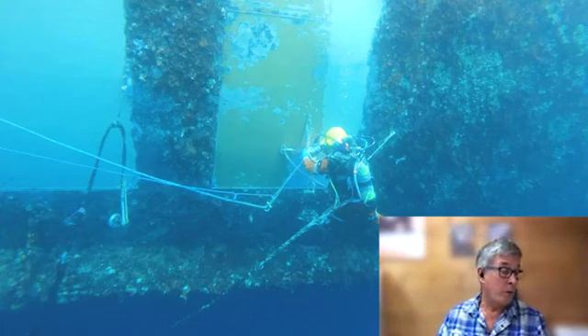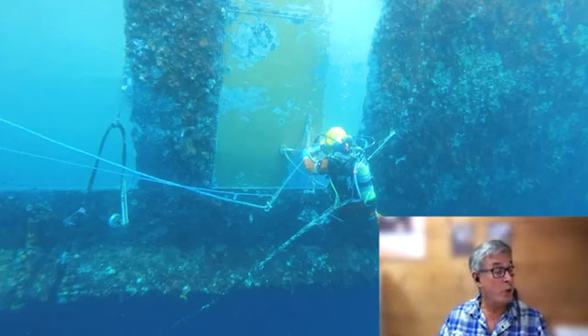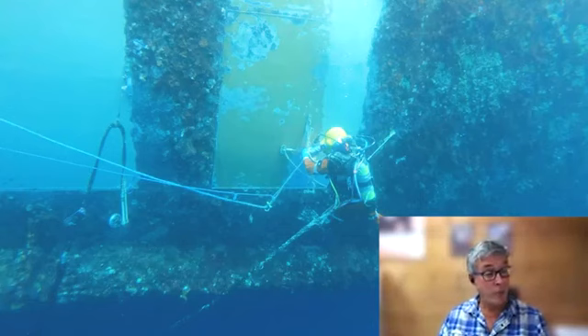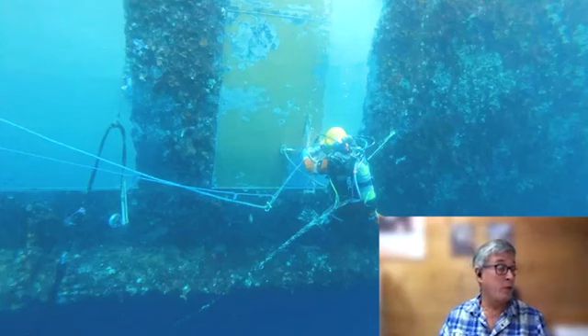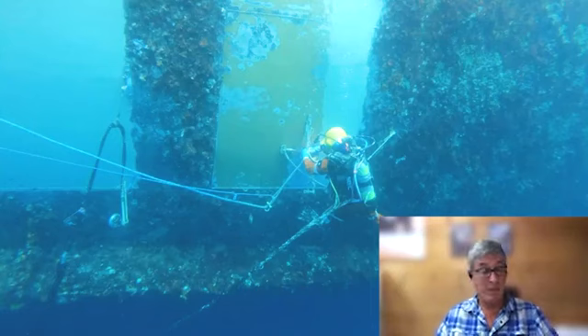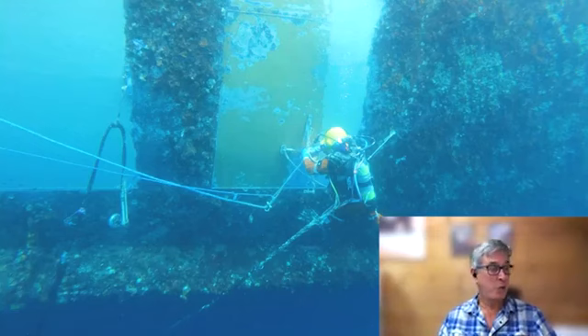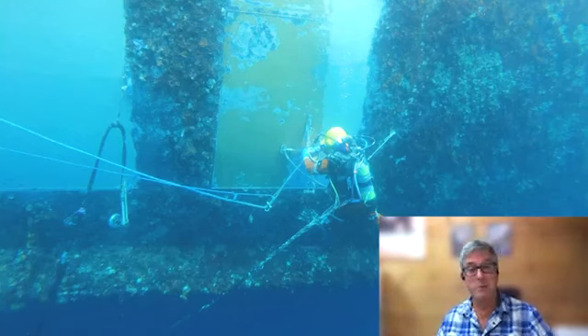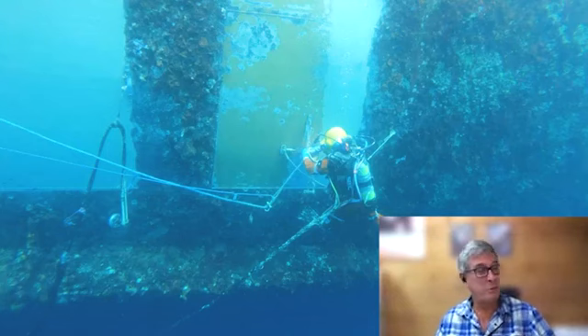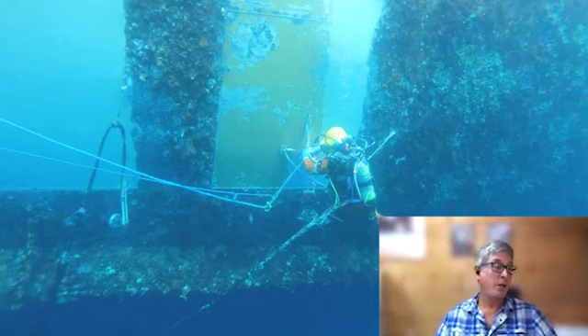5831. We apply the coating at about 250 to 300 microns per coat. We apply 2 coats. We have found through experience that when the coating, and this is really painter speak, when the coating looks right, it's about 300 microns. When it looks a bit uneven, it's probably well under 250 microns. And then when it looks really very, very thick and ridgy, then it's over the 300.